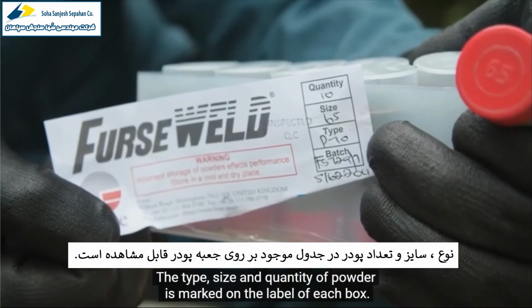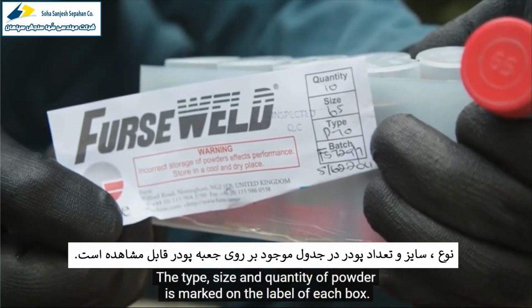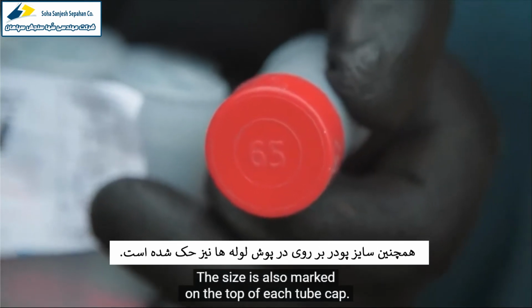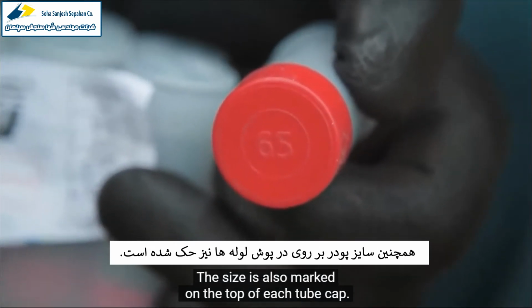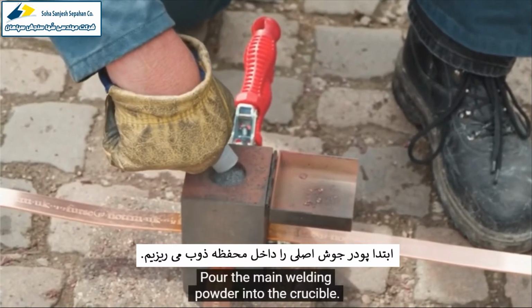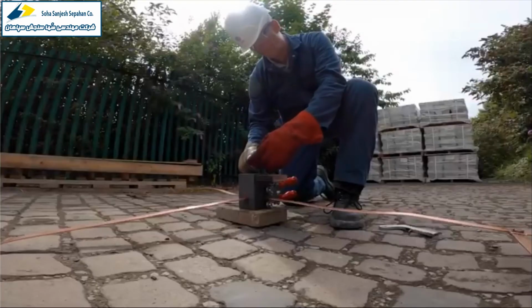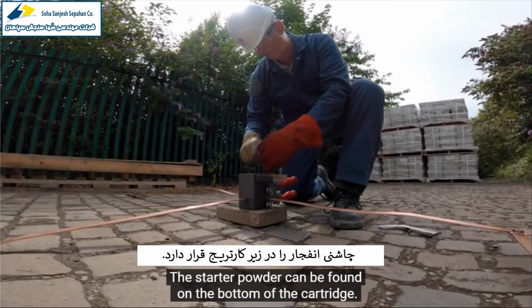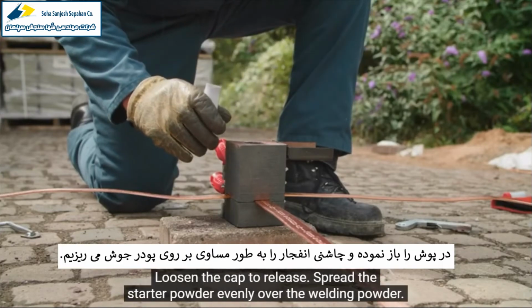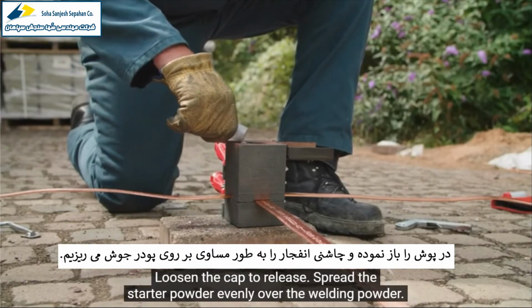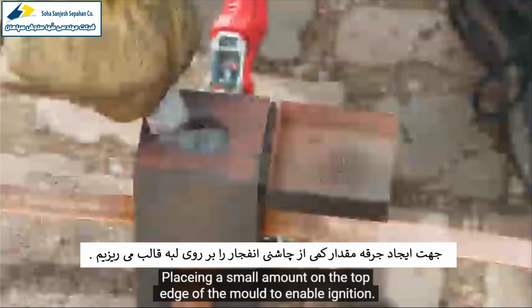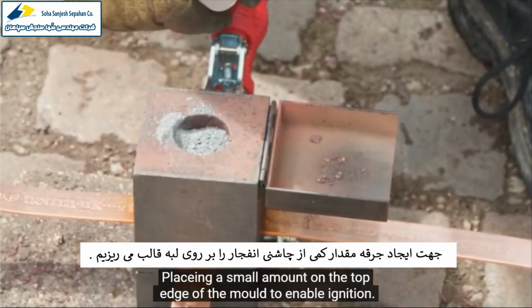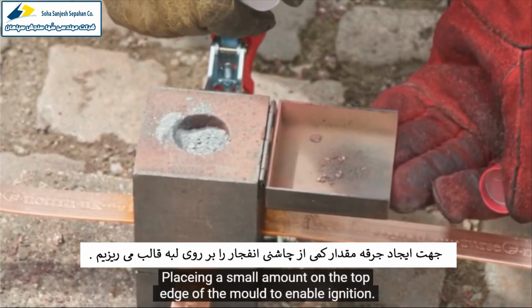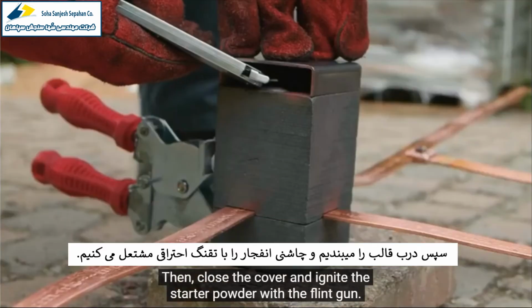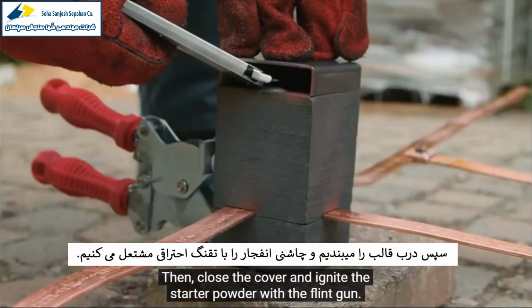The type, size and quantity of powder is marked on the label of each box. The size is also marked on the top of each tube cap. Pour the main welding powder into the crucible. The starter powder can be found on the bottom of the cartridge. Loosen the cap to release. Spread the starter powder evenly over the welding powder, placing a small amount on the top edge of the mould to enable ignition. Then, close the cover and ignite the starter powder with the flint gun.